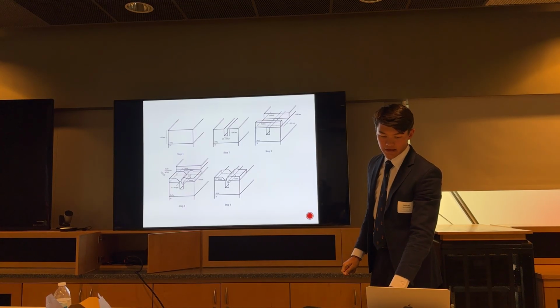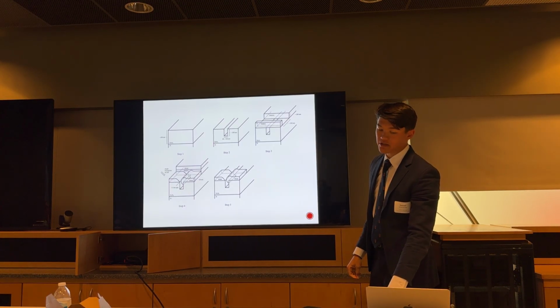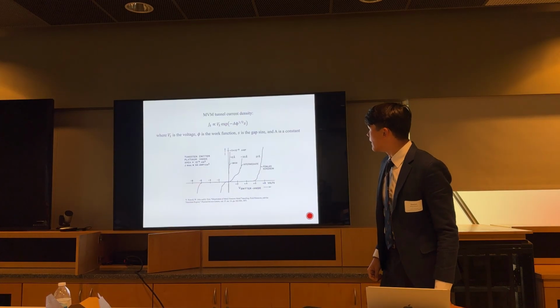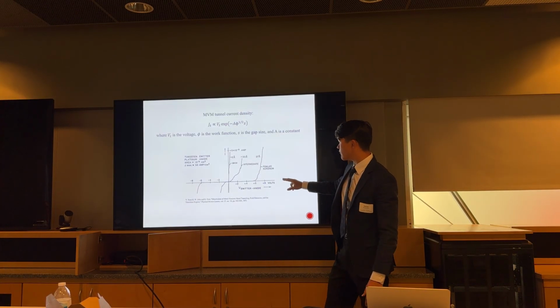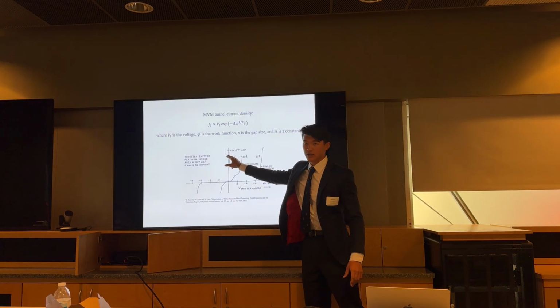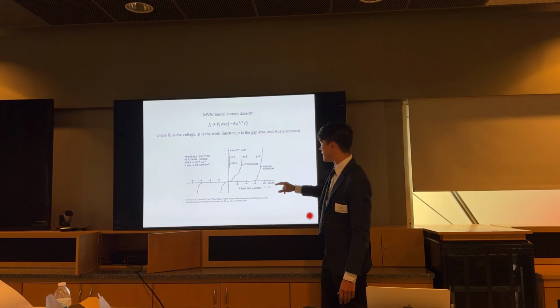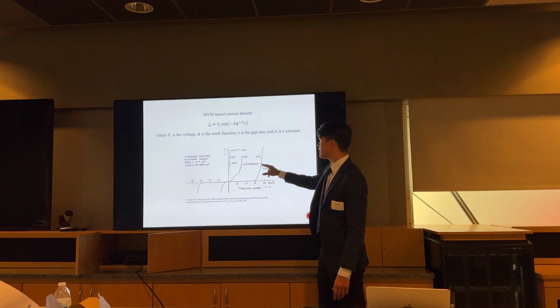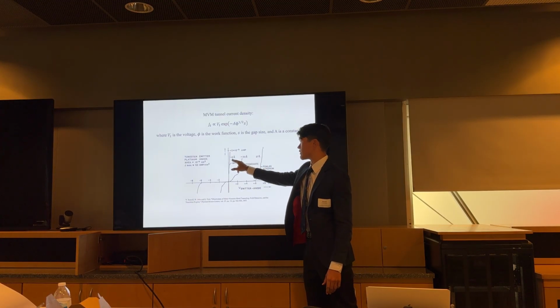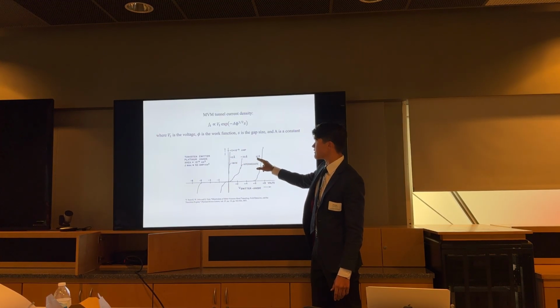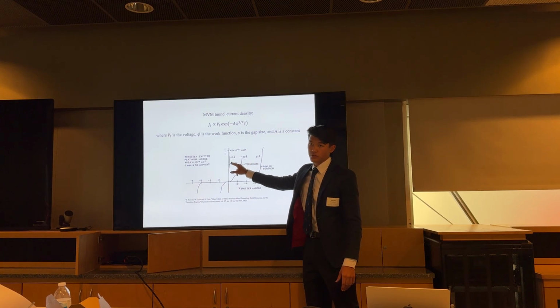And at the end, what we have to do is measure the electrical characteristics. Here is a voltage current plot, an IV characteristic plot. And it is showing the expected voltage current characteristic of devices with different separations between the two electrodes. So this is 2.7 nanometers, 2 nanometers, 1.2 nanometers.